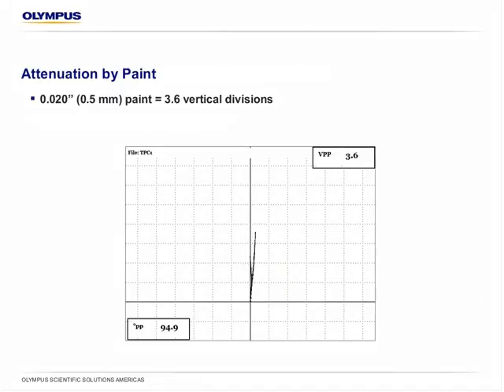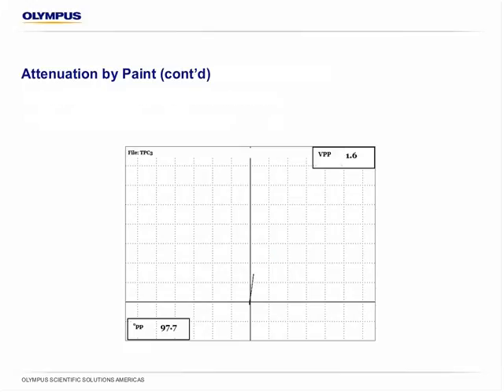Okay, that gives an 80% full screen height. If we add paint, now this is exactly the same defect being scanned with added liftoff or paint thickness, and with only half a millimeter of added paint, the signal drops to 3.6 divisions. It was 6 before without paint, it drops to 3.6. And as we increase the paint thickness, it's going to drop further. This is 1 millimeter, which provides 2.4 divisions. 1.5 millimeters of paint is 1.6 divisions, and 1 division, or 1.3, for 2 millimeters of paint.